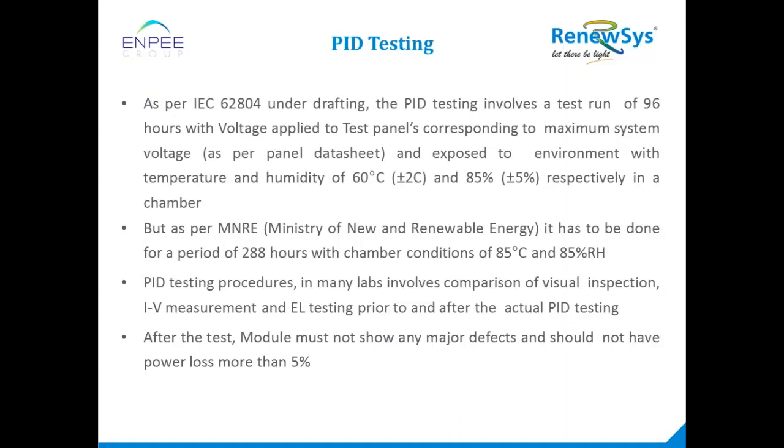Certain countries have their own PID testing standards depending upon the climatic conditions that they operate in. Typically, if you take India, which is a subtropical climate where the temperatures and humidity are on the higher side, the test conditions decided are 288 hours with a temperature of 85 degrees centigrade and RH of 85%.